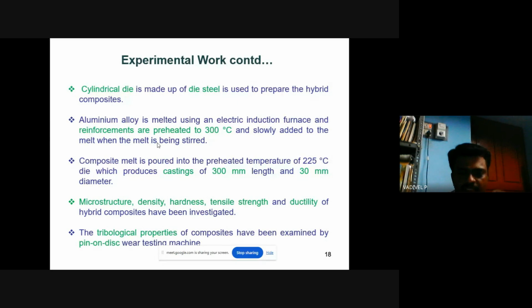Another important thing is that the die is also preheated, up to a temperature of 225 degrees Celsius. Here the die is preheated, and the reinforcement is also preheated. These are the main parameters, the main things we should focus on in this work. The casting which we produced is about 300 length and 30 diameter. After that, the microstructure, density, hardness, tensile strength, and ductility of this hybrid composite have been investigated.